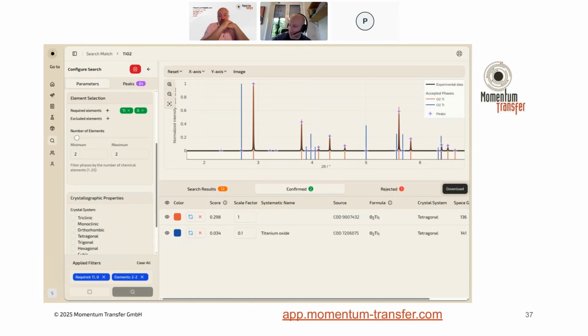And so we've actually developed our own phase identification tool, which we have in our platform online. In using this, we currently use the Crystallography Open Database, but also in our own analysis projects for customers and for people that we work with, we also use the ICDD, which is the International Centre for Diffraction Data database. And this has many, many thousands of reference structures that we can use to match and identify these peaks. In this case, again, I just showed this example of rutile and anatase, which is easily pulled by isolating the peak positions and intensities. And this is actually free for people to sign up and try out if they're curious. And it can also be used with laboratory source data. And then you can compare it to data measured with us as well.